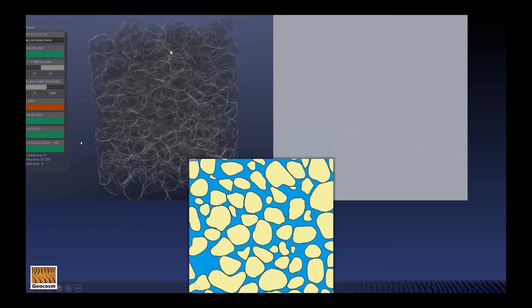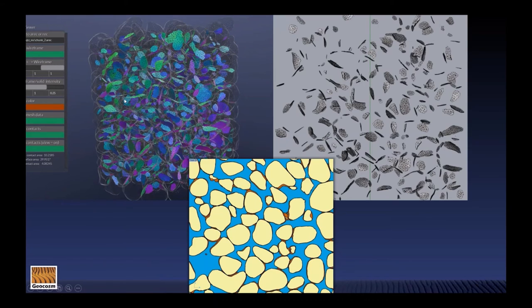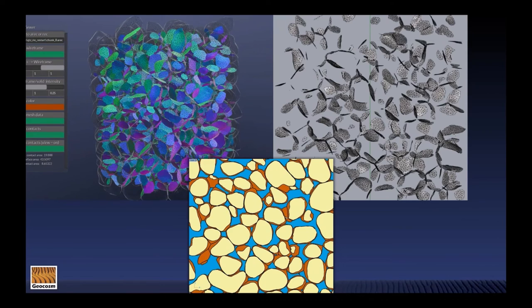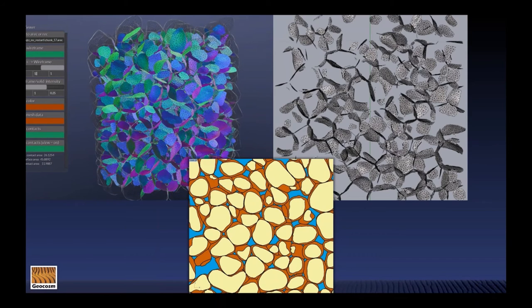So just going back to the contact part of the problem, here again, same grain pack, but what I've done over here is to make the grains pretty transparent, and I'm going to visualize just the contacts that develop between the grains as a function of quartz cement. And on the right, we also are going to look at that, but just through a thin slice in the 3D volume. So these things that look sort of like potato chips over here are the contact surfaces. These are kind of a toast slice-like view of those contact surfaces. And so we can see how they grow as a function of the quartz cement growth.